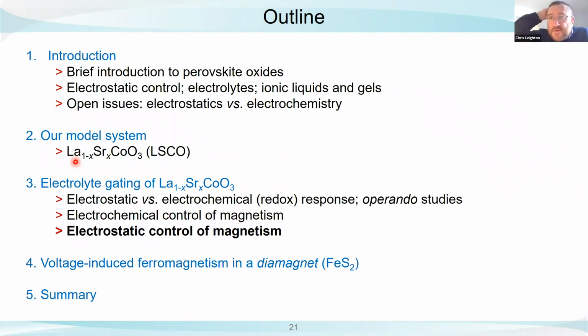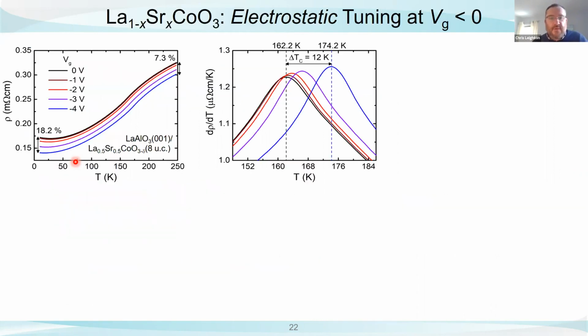We were also interested, however, to do the exact opposite, which is to start from 0 volts. I showed you that by going to negative voltages, we were able to get a predominantly electrostatic effect. We were interested, is it possible there to get reversible control of magnetism also? So here I'm going back to the films that I showed you at the beginning of the talk. This is 8 unit cells thick. We're applying now only negative voltages. We get a modulation of about 20% of the resistance.